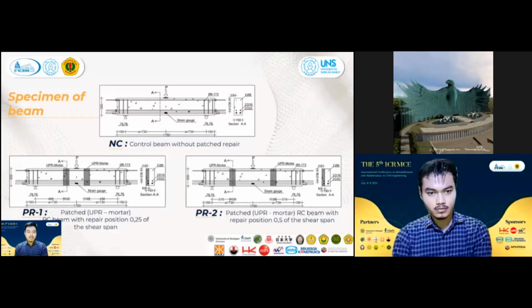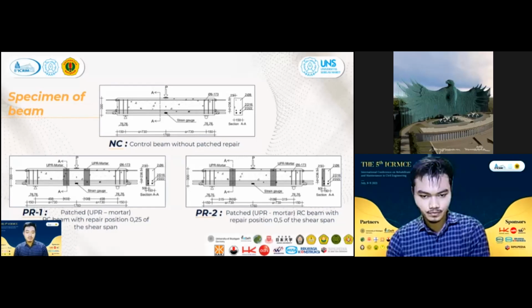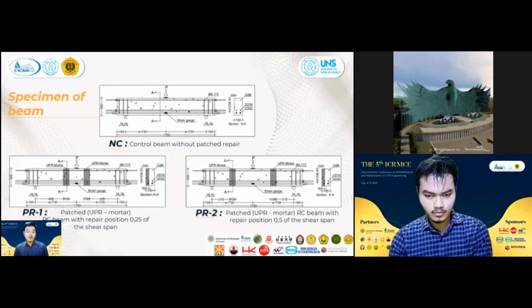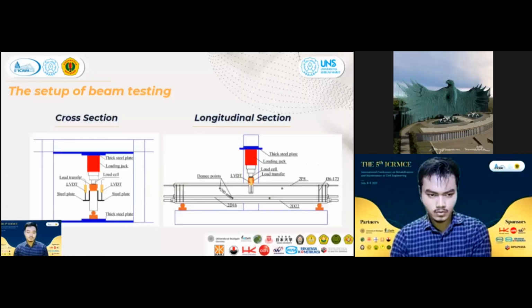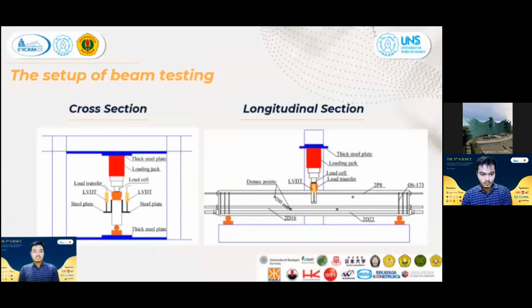Next, specimen of beam. Three different types of RC beam specimen with a shear span to effective depth ratio of 3 were prepared and tested, namely, first, NC, as a control beam without patch repair. Second, PR1, as a patch RC beam with patching position at 0.25 of the shear span. Third, PR2, as a patch RC beam with patching position at 0.5 of the shear span. Next, this is the setup of the beam testing.